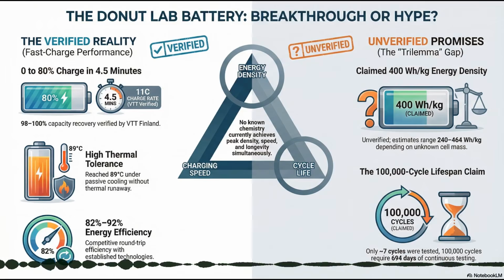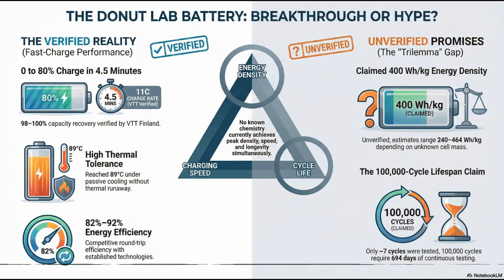Right. They hold 11C, that 286 amps, until the cell voltage hits the upper safety limit. Then, to prevent overvoltage and completely breaking down the electrolyte, they hold the voltage steady at that ceiling while the current tapers off. And even with that taper, VTT verified that it hit 80% state of charge in 4 minutes and 27 seconds. Which is astonishing. That is legitimate fast charging. That is comparable to refueling a gas tank.